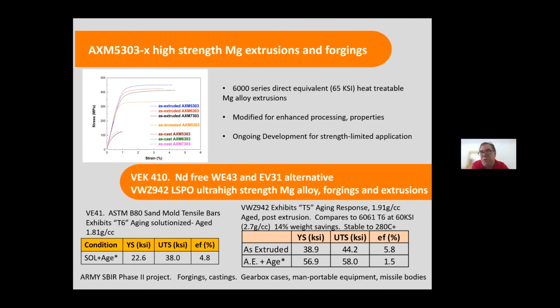VWZ 942, which is a long period stacking order. This is stable to above 280 centigrade, and in the age condition is directly comparable to a 6061, with much better thermal stability. So it's 57 KSI yield, 58 KSI ultimate as T5 aged. And this can take, again, stable to elevated temperatures. And so it's applications in military equipment, missile tubes, bulkheads, anything that's seeing high temperatures and very high stresses. So gun parts is one of the applications for this.